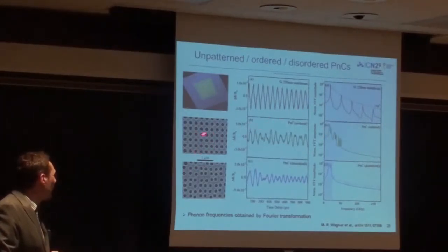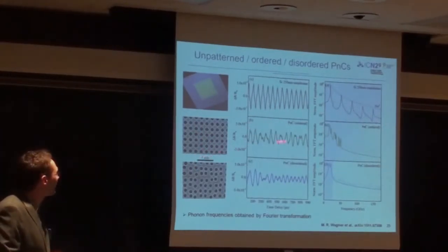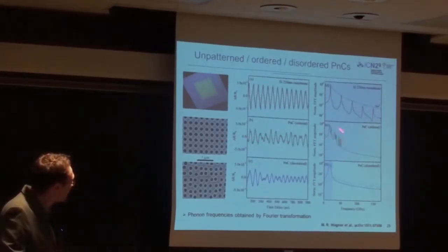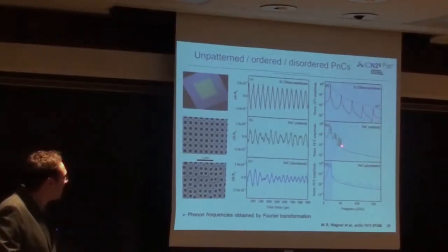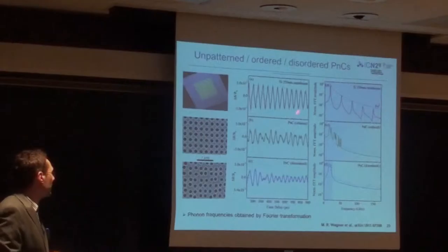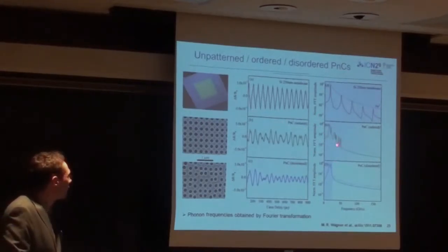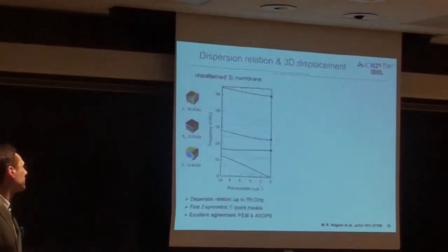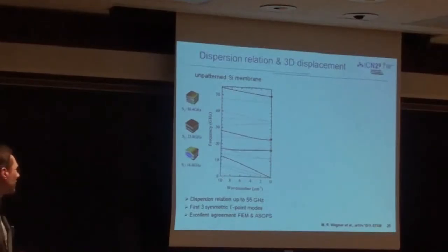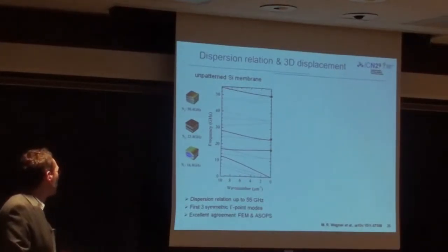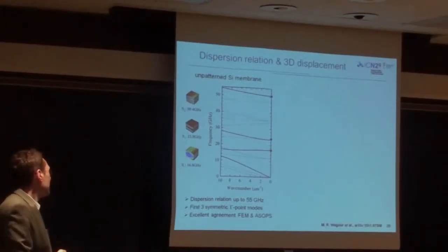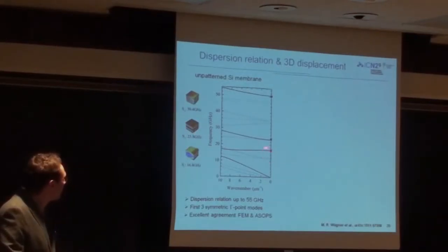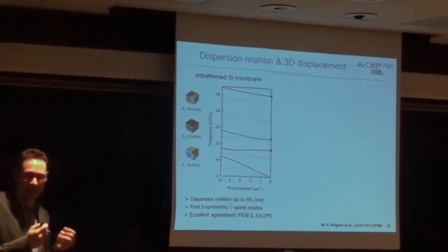However, if you introduce now this second order periodicity, this regular hole lattice, and you do the Fourier transformation of this time domain signal, first is that there's a very strong modification of the phonon modes, and you can see the appearance of several sharp coherent phonons in the low frequency range. And in addition, you can see that you're suppressing higher frequency coherent acoustic phonons. So what we've done is using again finite element modeling to see if this matches with the time domain spectroscopy, and you can actually identify the 3D displacement fields, and you see the experimental points here. They are in excellent agreement